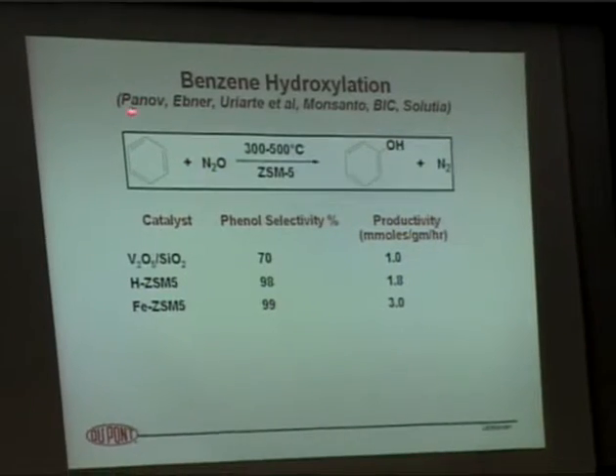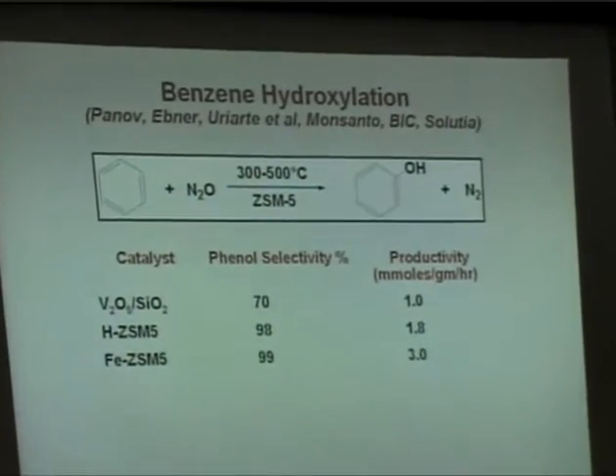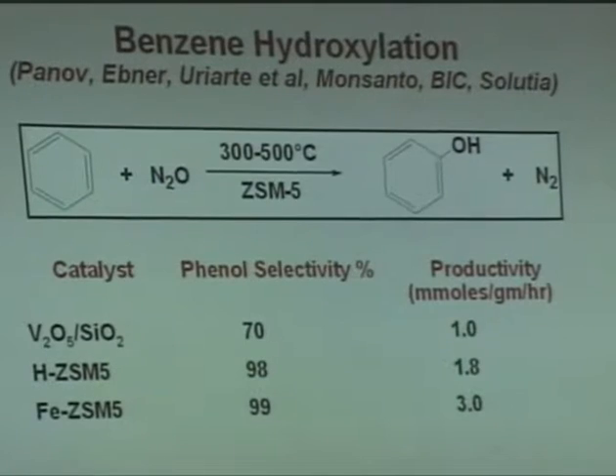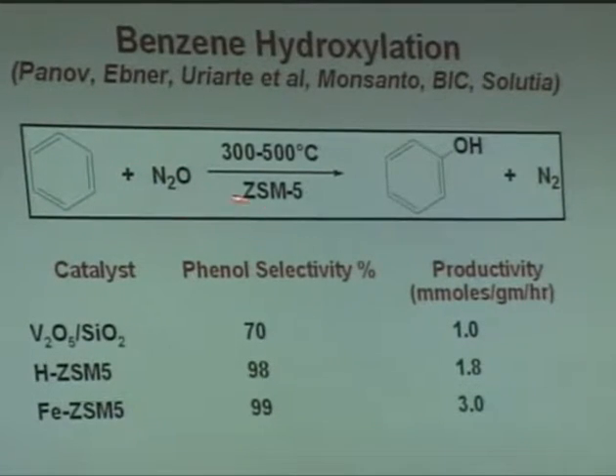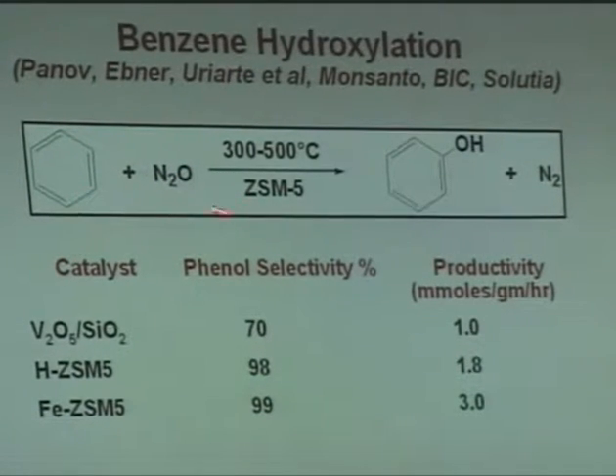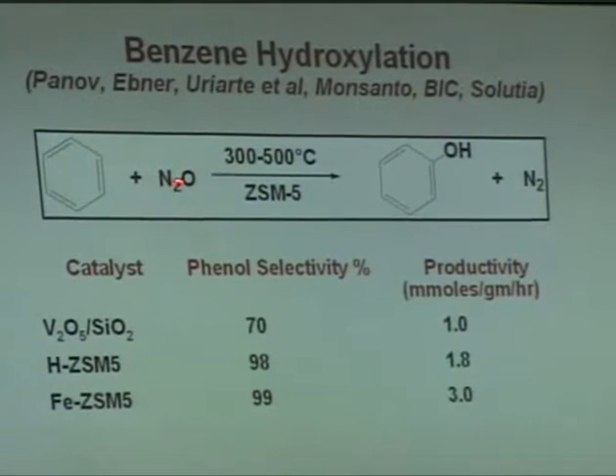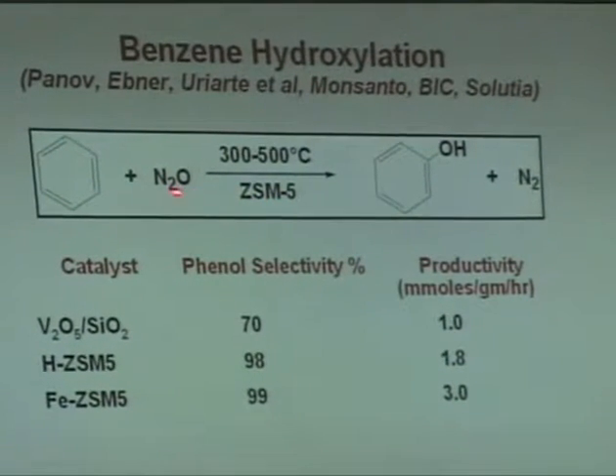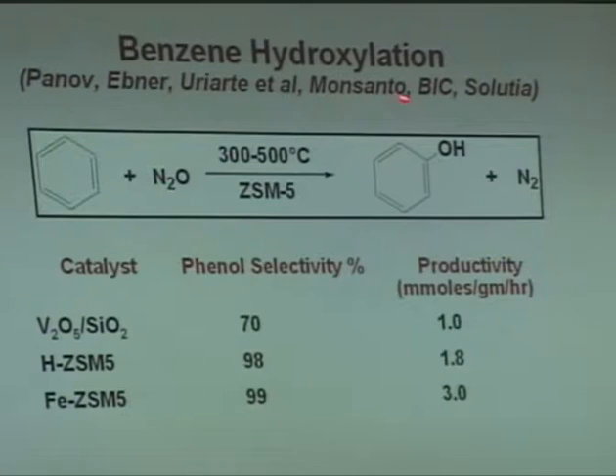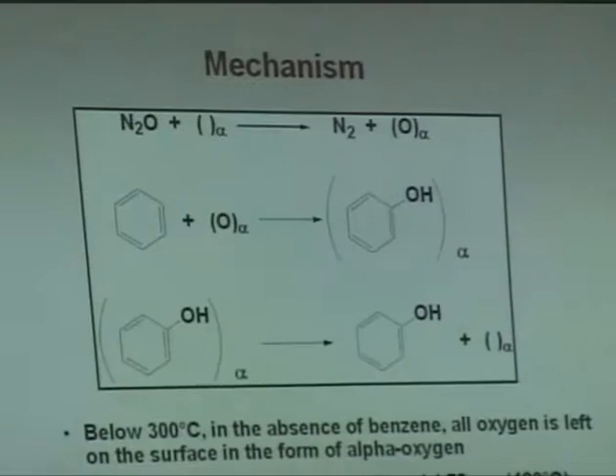This work was really pioneered by Panov at the Boreskov Institute of Catalysis. He did a really superb job, and he found that iron-modified ZSM5 was very, very, very active and selective for converting N2O and benzene to phenol and nitrogen. Selectivity is extremely high, 99% in this process. They then formed a partnership with Monsanto, now Solutia, to commercialize this technology. And I'll show you the status of that process in just a minute.